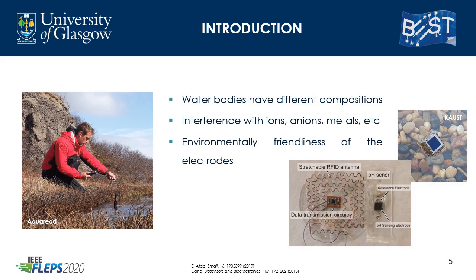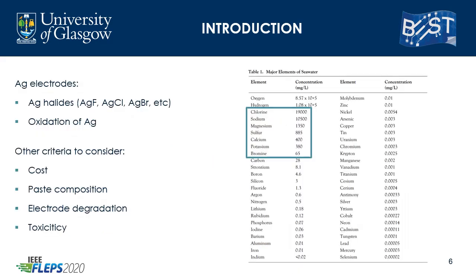In this context, silver and carbon seem to be popular choices, however, they have quite different properties. Silver seems to be a popular choice due to its high conductivity and lower cost when compared to other metals. But chemically, silver is a reactive material. It is known to form salts with elements from the halogen family, and when we look at seawater composition, we can notice a high concentration of such elements. Particularly, chlorine can be a problem. Silver also easily oxidizes. Therefore, in some cases, an alternative conductive track could be more advantageous.